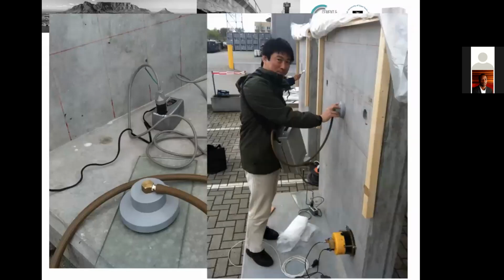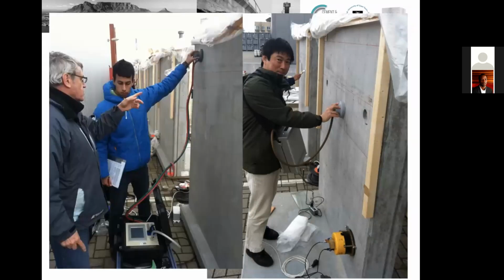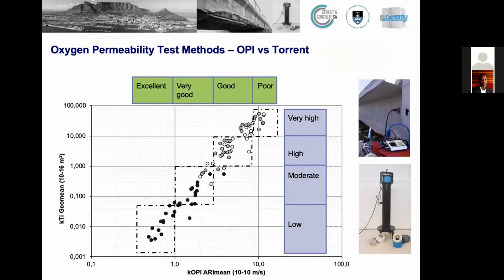And lastly, this is the Torrent test, which measures the permeability of the concrete in situ. A very useful test, similar to the other Japanese test method I showed you, but much more practical. And we also have worked with this test method a lot in our laboratory. And that probably is the leading test method worldwide applied for designing concrete structures for carbonation and chloride ingress, the Torrent tester that you can use in situ. We have compared the Torrent tester to our local oxygen permeability index test. They both work on very similar principles in terms of measuring the permeability of concrete under a pressure gradient.